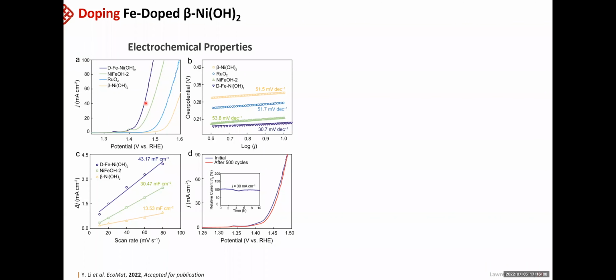really good. I'm not so sure this is a new type of catalyst as Professor Hu introduced, or the classical catalyst. We didn't really go into the mechanistic studies at the atomic level. But anyhow, the overpotential at 10 milliampere per centimeter square was quite impressive. It was only 194, below 200. And it shows a very low Tafel plot slope, which means it has very good kinetics and also the active sites. And even after 500 cycles, they were quite stable.